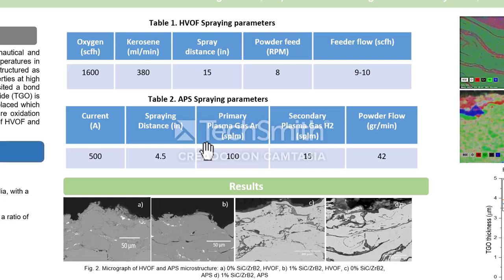Once the coatings were fabricated, the samples were exposed to thermal oxidation cycles, 100 cycles in total. Each cycle consisted of 40 minutes of heating and 15 minutes of cooling at a temperature of 1100 degrees Celsius.